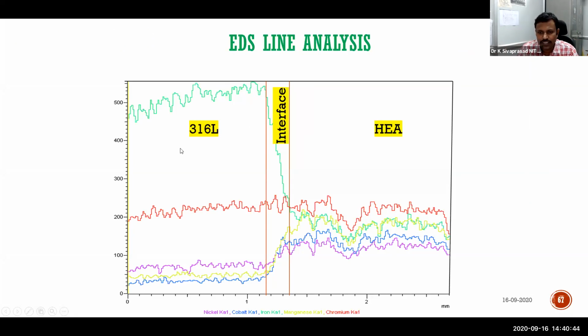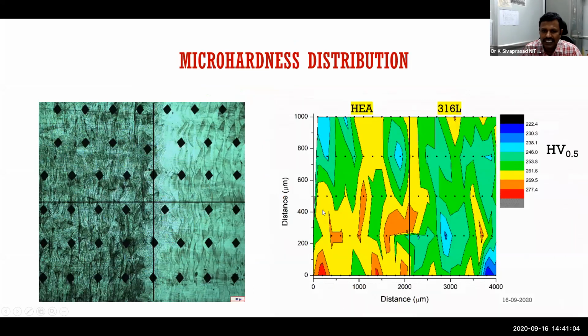Only iron, you can see that iron is very rich in this and so low in this one, but compared to iron, all the other elements show almost a gradual variation. So this is evidence that there are no strong residual strains associated with the interface. So this is proved. Then the hardness profile was taken to see whether any extremities are associated with it.